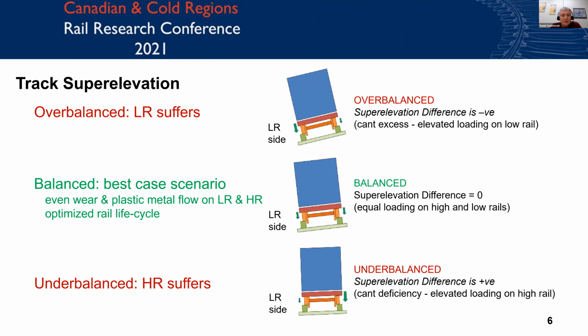That's the overbalanced. If you have an underbalanced condition, the high rail suffers, and you have a cant deficiency, and the super elevation difference is positive, and then you have more loading on the high side of the rail. So since the breaks happened on the high rail side, we decided to look at the underbalanced condition and find out what the cant deficiency is in the curves that we had, and then how we can go about inspecting that in track.